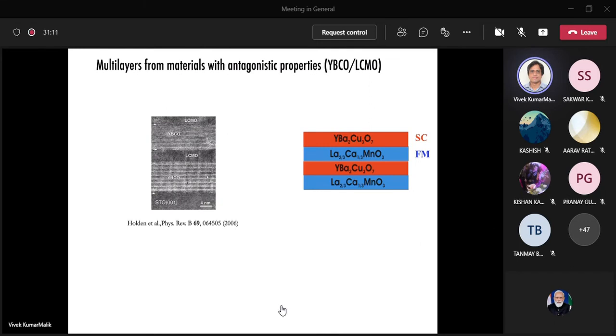So you can see the unit cells of the YBCO. This is large because along the C-axis it is about 11.6 angstrom, and LCMO has a lattice constant along the C-axis of about 3.87 angstrom. So you can see that this is a large unit cell, which you can see directly over here. Whereas the in-plane lattice constant is almost the same for both materials, around 3.9 angstroms. So you can grow these layers artificially, YBCO, LCMO, and so on, superconducting and ferromagnetic. And then you can try to see what happens in this case.